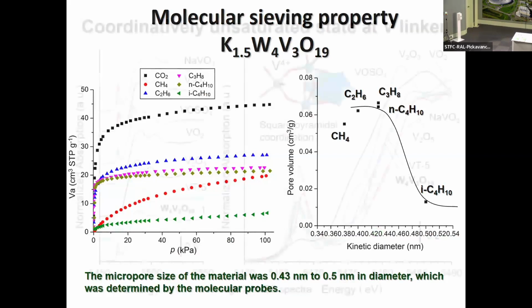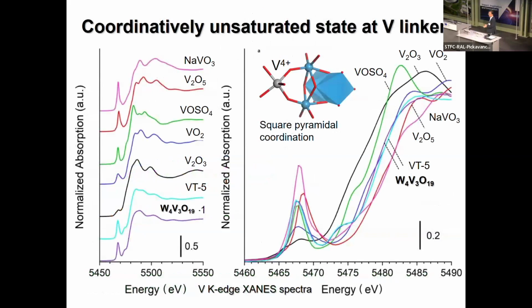So you can expect performance for the ammonia SCR reactions. Before going into that, I have to show some catalytic properties of these materials. We conducted the analysis of the structure of a vanadium species by using this analysis. This kind of analysis supports that the vanadium species had a square pyramidal coordination just between two Keggin tungsten vanadium oxide.